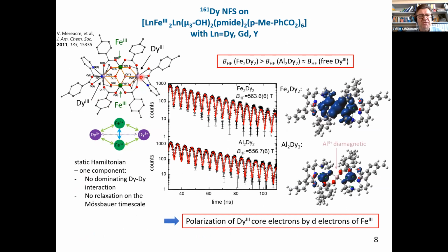It has 2 dysprosium ions and 2 iron ions. So the iron ions are basically spectator ions for the dysprosium. And what did they do? In these molecules, they could replace the iron in the middle here by a diamagnetic aluminum. And when you look at the hyperfine field, that's 556 Tesla. But if you put the iron in and the structure is the same, the hyperfine field really increases by roughly 7 Tesla. So that's a molecular effect. And you have a polarization of the dysprosium core F electrons by D electrons of the iron 3.